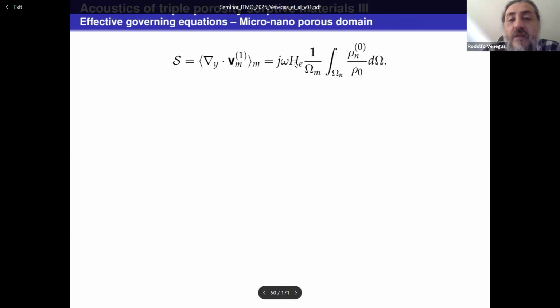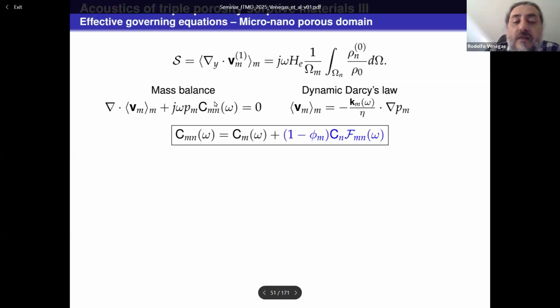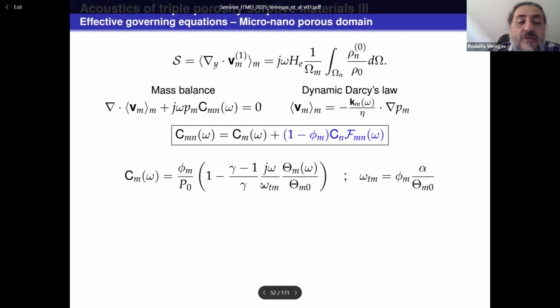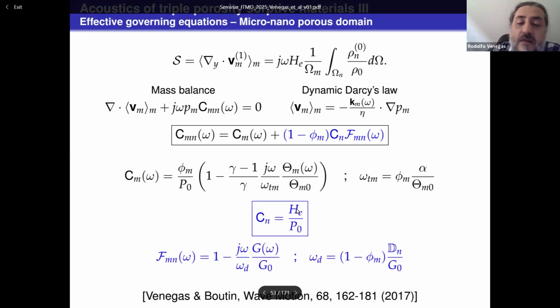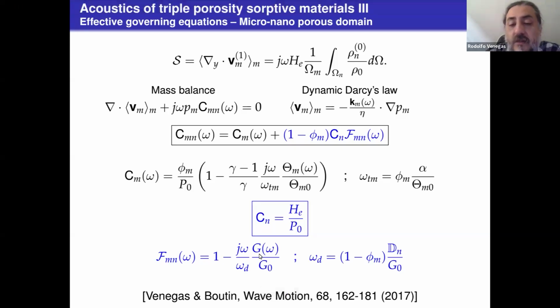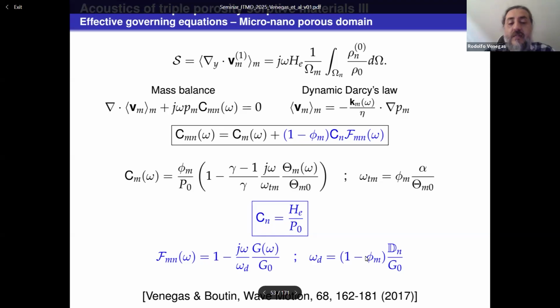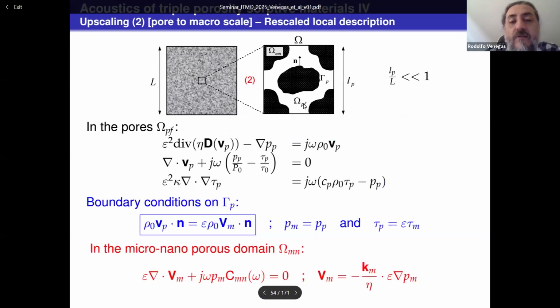So this is J omega HE multiplied by the average of the local density field over, in this case, the equilibrium density. So we can write the mass balance in a way similar to the classical way, with the difference that the permeability is now affected by rarefaction effects, and the compressibility has two components. One of them comes from the micropores, and another component comes from the nanopores, and this mass diffusion that occurs in between these two domains. And this is the expression for the compressibility, and the compressibility of the nanopores is this linearized effective equilibrium constant over the equilibrium pressure, and F takes the classical form of a relaxation function if we were to consider this in time domain. So this was published in this work, and we use this formulation to couple it with the Navier-Stokes system now formulated on this omega PF pores.